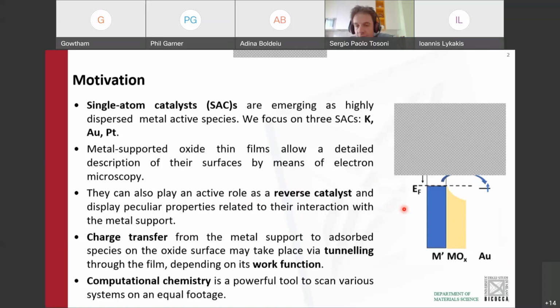It is possible to transfer an electron from the metal substrate to any adsorbate that you put on the oxide thin film surface, or vice versa, via electron tunneling through the oxide film due to the very small thickness of the film. And the key parameter to characterize this charge transfer phenomenon is the work function. The work function is defined, as you can see in the picture, as the energy difference between the Fermi level of the metal and the vacuum level.